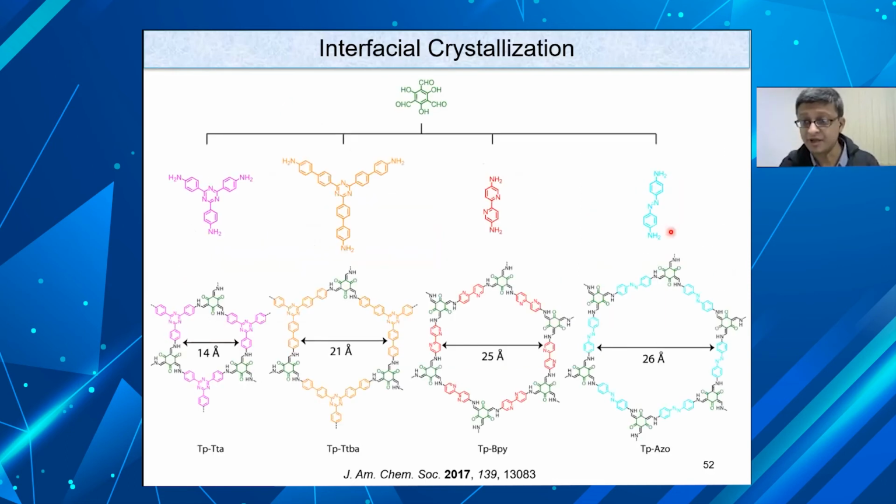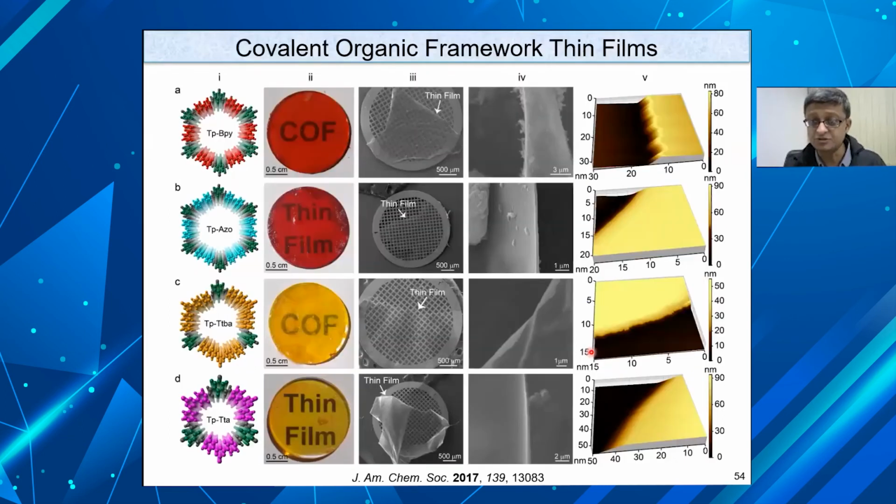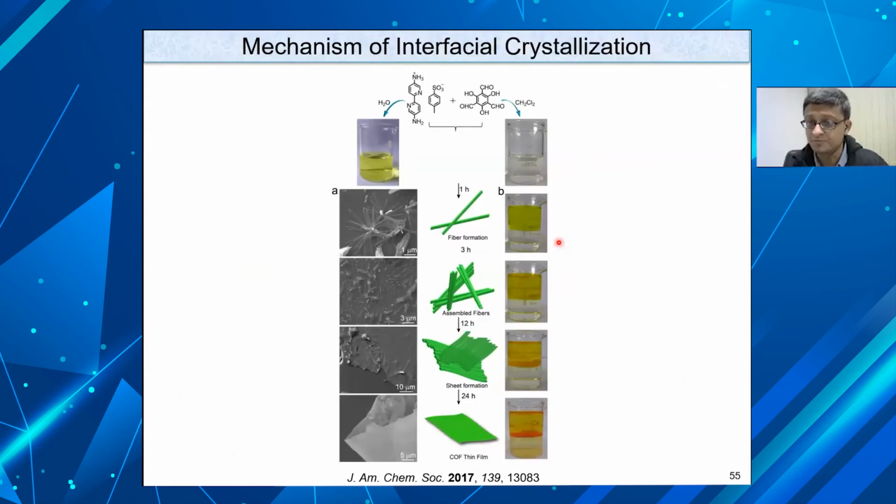These thin films, I'm so proud to say, you can vary the pore size of the film. Number one. Not only that, these films are microporous by themselves, just the film pieces. And the important part is, if you take this film and check, you can see how uniform these films are. Of course, there is a little bit of deposition, I won't say no to it, but overall you could make different sizes. You could make a 100 nanometer film, a 1 micron film, or a 120 micron film. That is totally up to you.